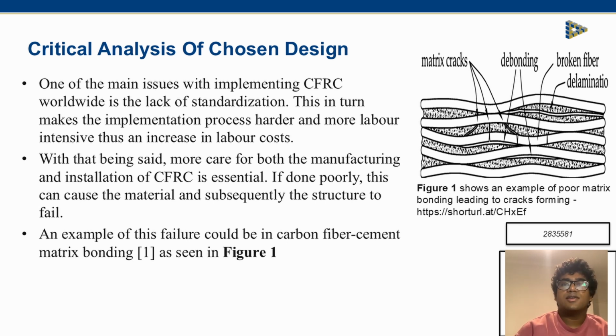If done poorly, this can lead to the material and subsequently the structure to fail. An example of this failure could be in carbon fiber cement matrix bonding. When the surface of carbon fiber is smooth, it can lead to poor bonding with the cement matrix and thus leads to cracks forming, which allows for crack propagation to take place. Also, poor bonding can lead to poor stress transfers between the layers.